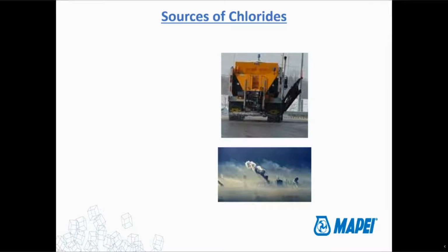So I touched a little bit on the sources of the chlorides earlier, but just to rehash that, there's really two sources. They can be internal sources or external sources. The internal sources can include things like the mixed water. A lot of municipalities around the country actually do use chlorides to help treat water. So if you are getting your mixed water from the faucet, like you should be, there's a good chance that there's actually some chlorides in that water that you're using to mix your concrete. It's very, very common.